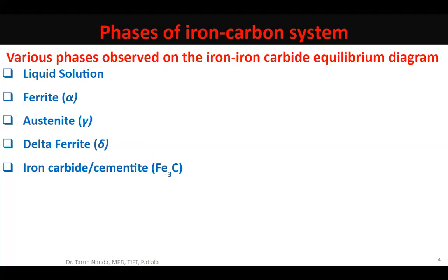It does not break before us over an observable period of time, but it always has an urge or tendency to dissociate into iron and graphite, because the free energy of that system is lesser than the free energy of a cementite system. But even at high temperatures like 700 degrees centigrade, that would take about thousands of years to happen.